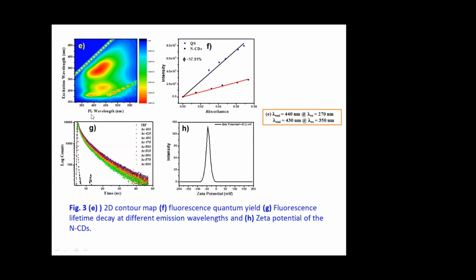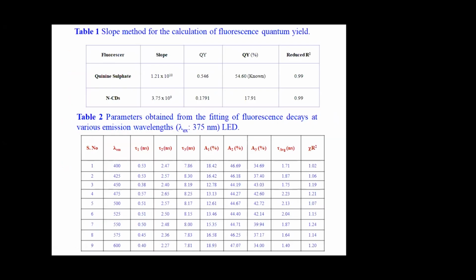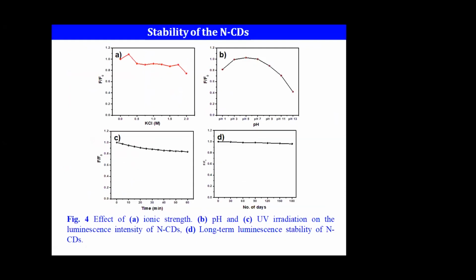Then we go for lifetime analysis to see what kind of components are present, more than one component, so you can see multiple components are there. The quantum efficiency we found was higher than the algae, almost 18%. You could also see that the negative charge on the surface potential is larger than what we saw in the algae material. This is how, as you change the source of the raw material, the surface functionalization and doping differ. We also measured the quantum efficiency by the relative standard method, which gives a better way of measuring quantum efficiency.